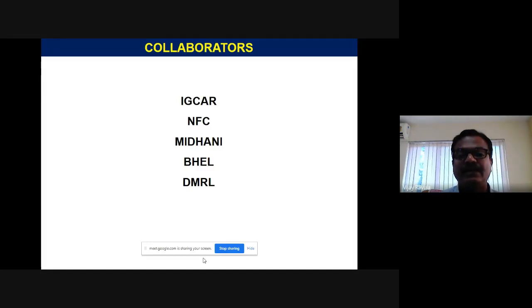And I will start with strengthening, oxide dispersion strengthened steels. When you say strengthening of any material, it comes from grain refinement, which is the famous Hall-Petch relationship. And if you do cold work and put a lot of strain in the material, the strength also goes up. And of course, solid solution hardening, where you can put carbon or other alloying elements like chromium, tungsten, or moly.